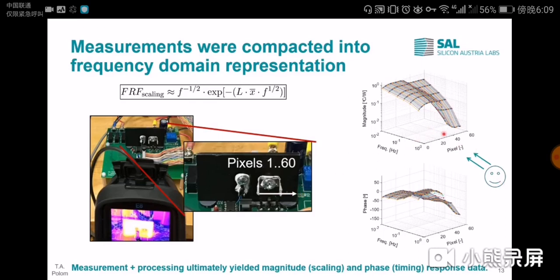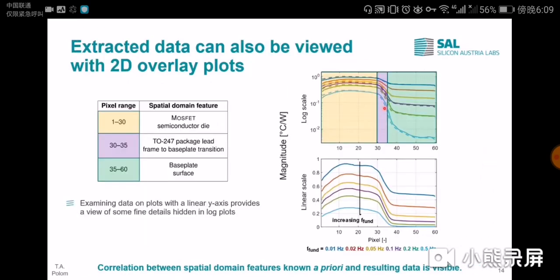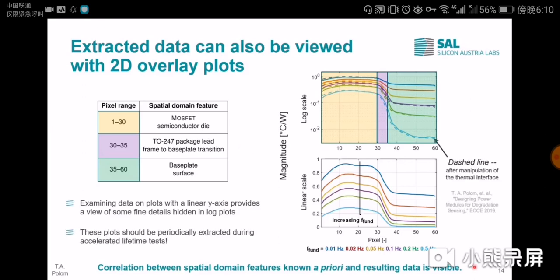Now imagine that we're looking into one of these 3D plots in the direction of this here. So this page is now using color in order to show how the certain spatial domain features, such as the MOSFET, the transition between the TO247 package and the base plate, and also the base plate surface, correspond to the data that we extracted. The top plot is showing data with a logarithmic y-axis and a linear x-axis. The bottom plot is showing the data on a linear plot, and we can see that we have additional detail of the semiconductor device surface that we're able to see with this linear plot. Ultimately, correlation between spatial domain features which we knew before doing the experiments and the resulting data is visible.